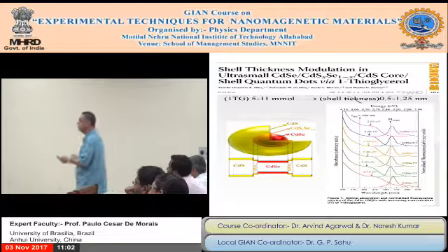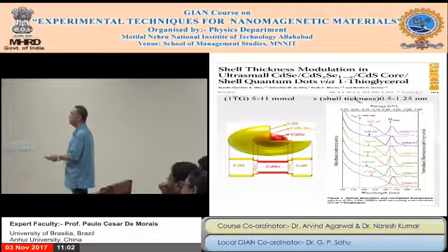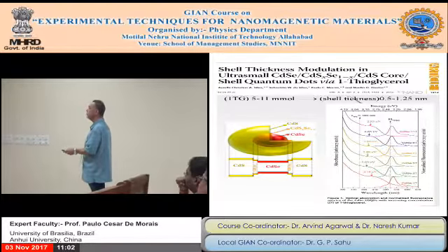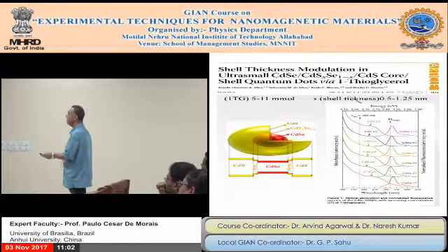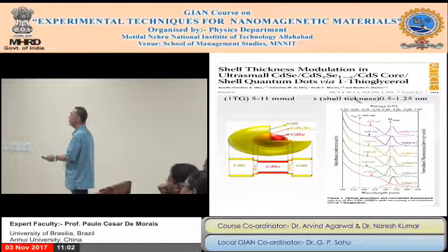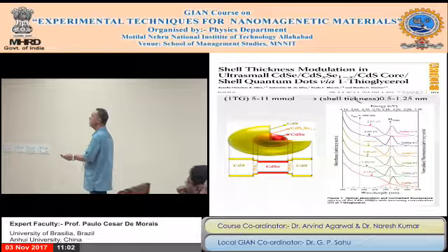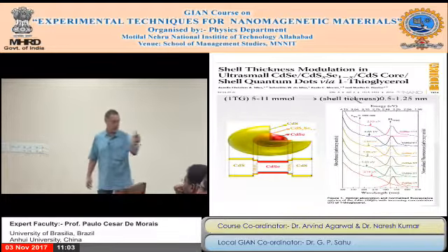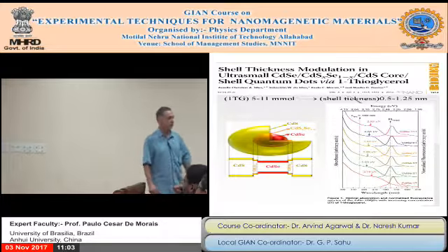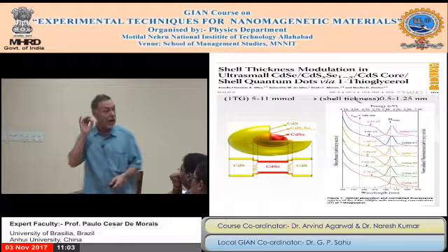If you look here, this is the first absorption, and then you can see the absorption moving to different positions. Likewise, you can see the PL line moving. So here's the first PL line, it moves a little bit, moves more, moves a little bit more, which means this sample is smaller. That's the smallest one. So we managed to modulate the size precisely.